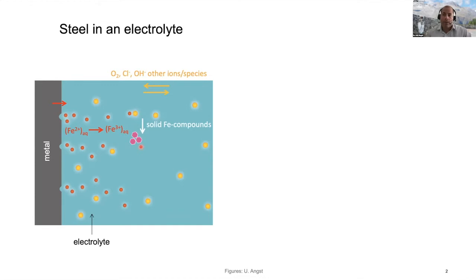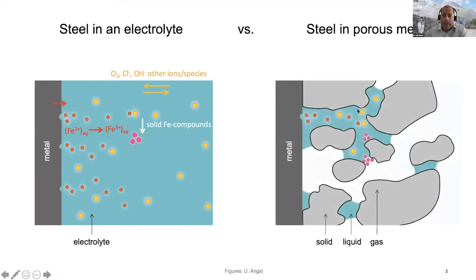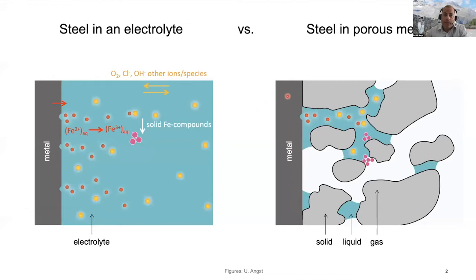Now, if we are in a porous medium, we have a range of very similar processes occurring, but those processes can only occur in the liquid phase. So it's the same reactions and transport processes occurring here in the liquid phase. But the difference now is that the metal is not only in contact with the liquid, but it is also in contact with solid phases and with pore space that may be air-filled, so that we don't have a bulk liquid electrolyte in contact with the metal, but perhaps only some adsorbed layers of water molecules present on the surface of the metal.